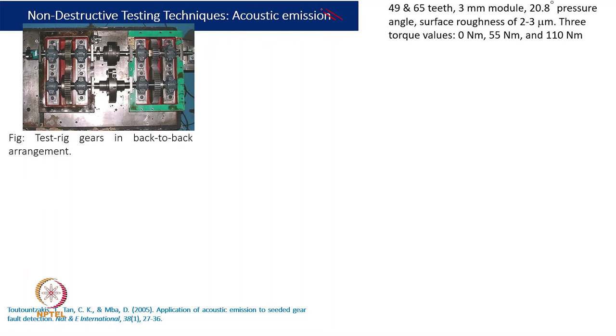Let me cover one example. Of course, this example has been picked up from the literature. We say there is a test rig having a back-to-back gear arrangement, and one pinion has 49 teeth, the gear has 65 teeth, and the module is 3 mm. Of course, generally we go with a pressure angle of 20 degrees, but in this case they have kept 20.8 degrees. Roughness has been kept on a higher side, something like 2 to 3 micron, which is much higher, right? They tested for 3 torque levels, 3 loading situations.